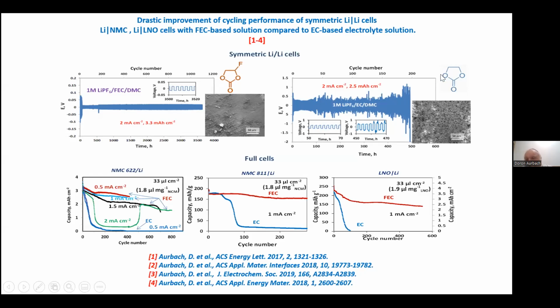When we use conventional electrolyte solution based on the solvent ethylene carbonate, we see the voltage profiles are unstable, and when we look at the morphology after hundreds or thousands of cycles, we see catastrophe, while here we keep the morphology relatively stable, thanks to the unique surface chemistry that we'll discuss. Now we can go to high energy density batteries. Simply take the nickel-rich materials that we discussed before, like NCM with 60% nickel, 80% nickel, and even 100% nickel, LNO, and we demonstrate that when we use conventional electrolyte solution, we have failure. But when we use our favorite solutions, we have stabilization, thanks to unique surface chemistry on both the positive and the negative electrode.